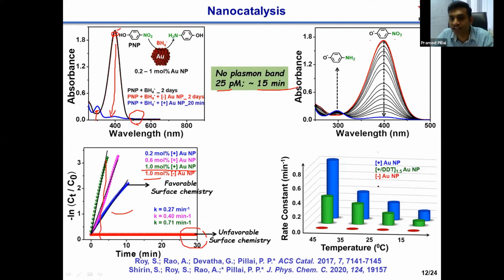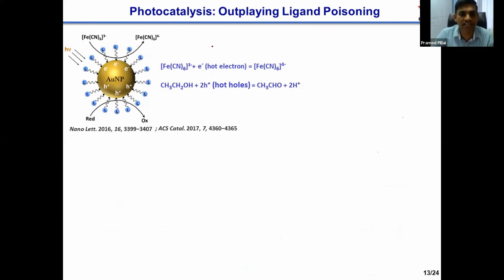So what we have achieved here is that we can design the nanoparticle in such a way that the same nanoparticle can act as a catalyst. At the same time, it can act as a non-catalyst. So this is a unique information which was not available in the literature. So what we have done is we have converted the same nanoparticle as a catalyst or as a non-catalyst. So we believe that the ligands that are present on the surface of the nanoparticle are acting as gatekeepers in controlling the catalytic reactions.